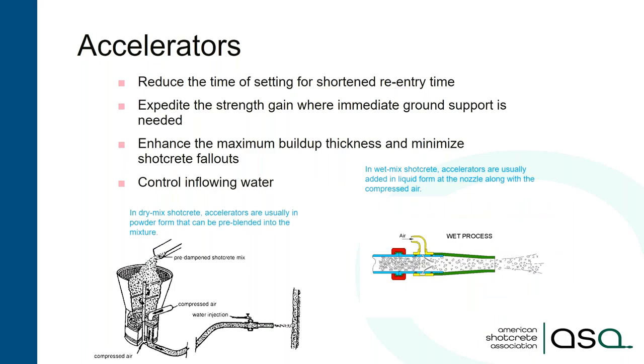Accelerators increase the speed for the cement to set, so you get more strength earlier. This means you don't have to wait as long before the structure has capacity. It also allows you to increase the buildup thickness and helps control water inflow when applying Shotcrete on wet surfaces. Accelerators in dry mix Shotcrete are typically added in powder form directly into the mix, while in wet mix Shotcrete they are typically added in the airstream right at the nozzle.